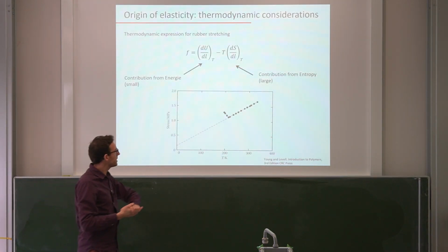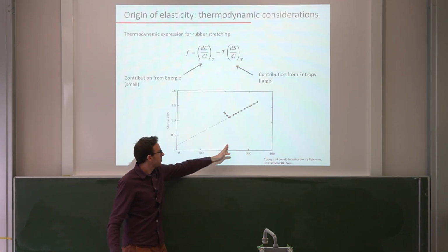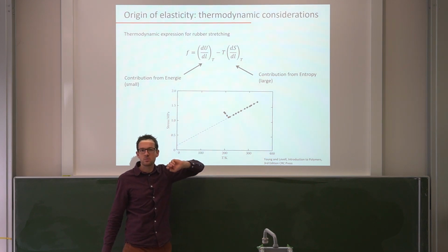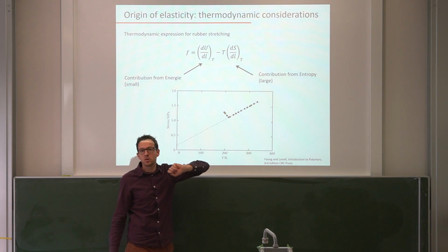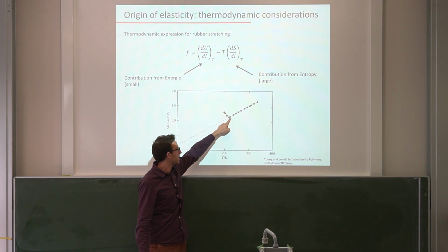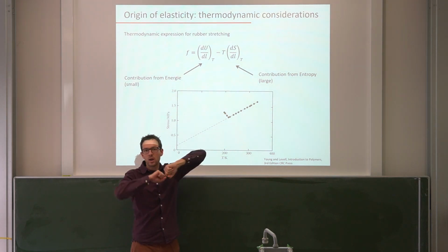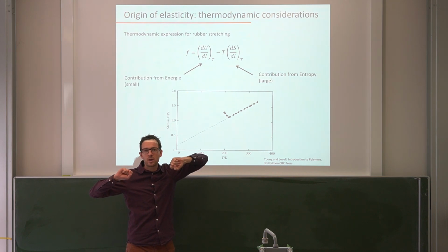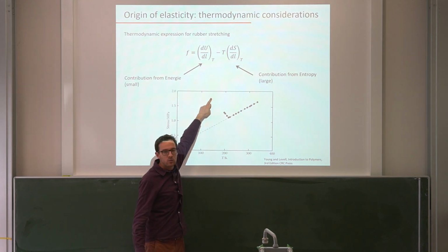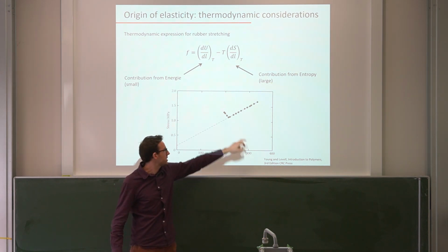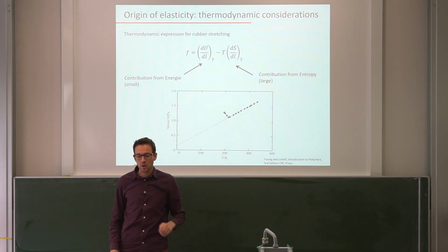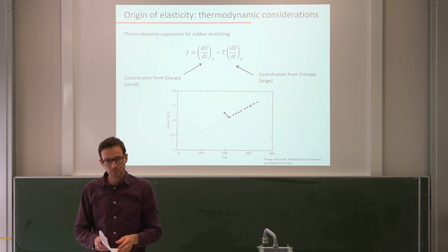So what's the answer here? Well, very clearly, from this point on, the rubber doesn't behave as a rubber anymore. No? And this is the glass transition temperature. Here the chains suddenly become very stiff and you cannot pull it anymore. And then, of course, it becomes stiffer and stiffer as you decrease the temperature because the thermal expansion coefficient is positive. But this is where, if you want the definition of a rubber, breaks down.